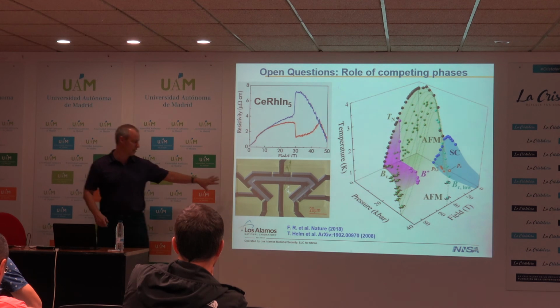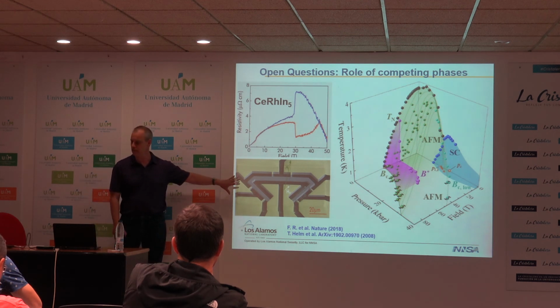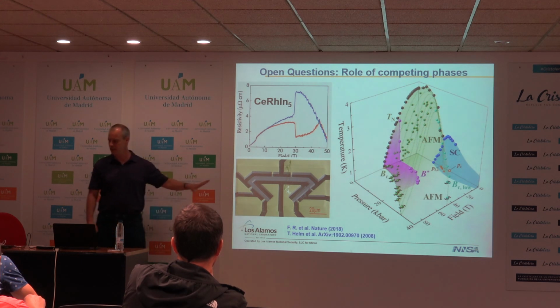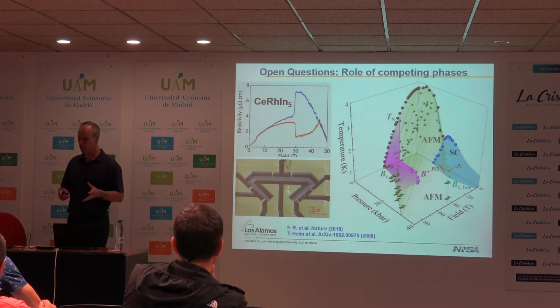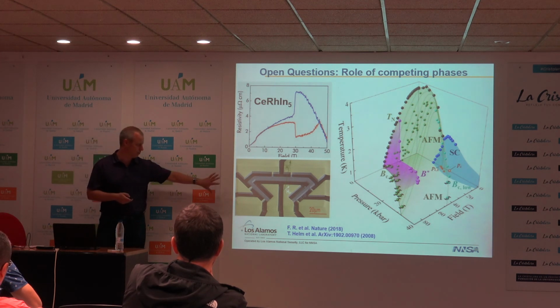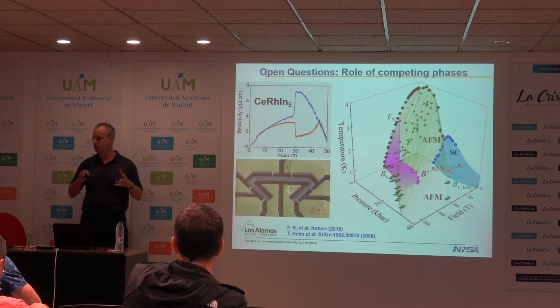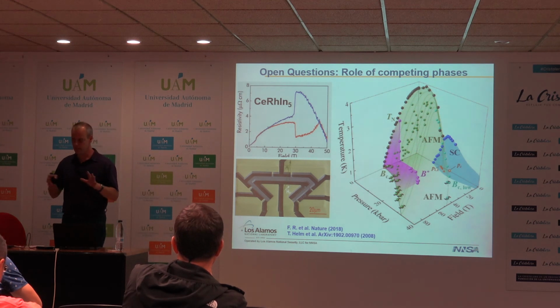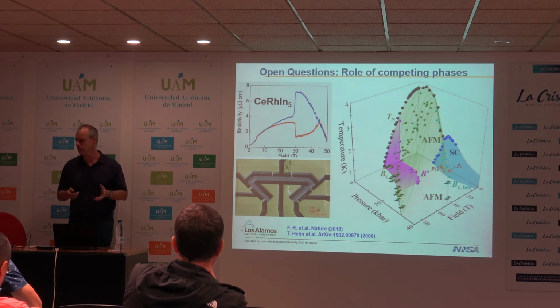True, cracking the FIB samples is an issue. Surprisingly, these small samples, and it's not clear why, actually seem to be a little bit more robust to strain. And I'll show an example in just a slide that you might be able to twist these structures a little bit more. So in fact, maybe they are a little bit more robust to pressure inhomogeneities and other features.